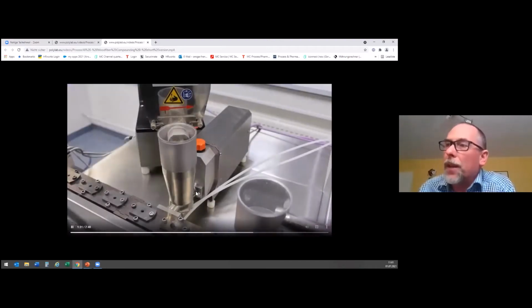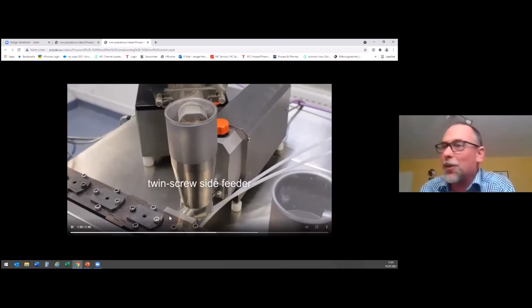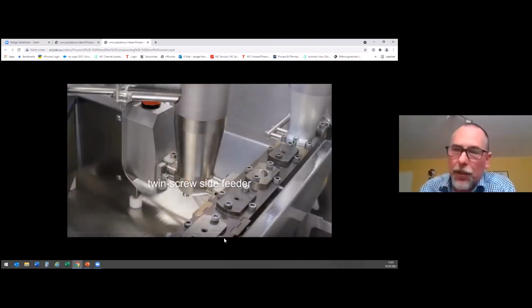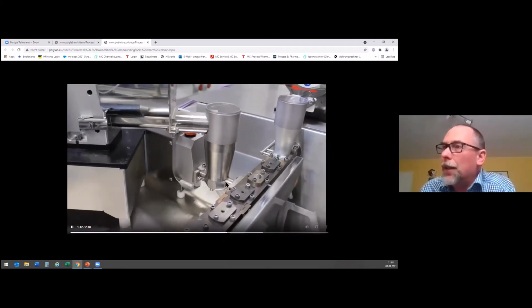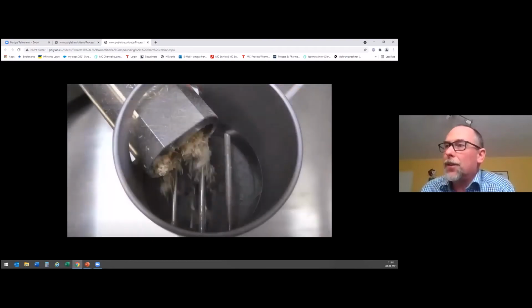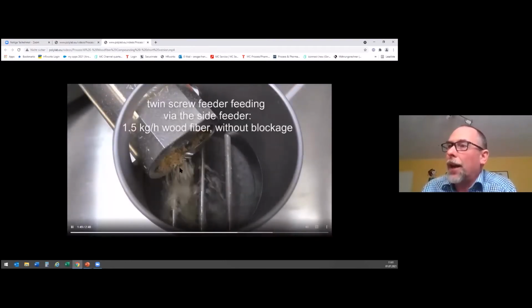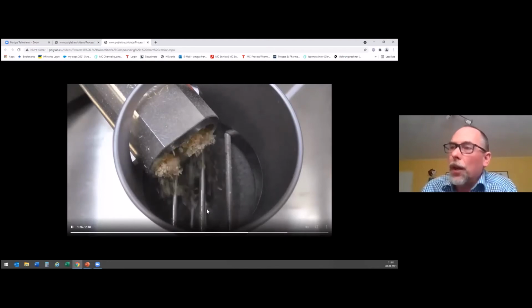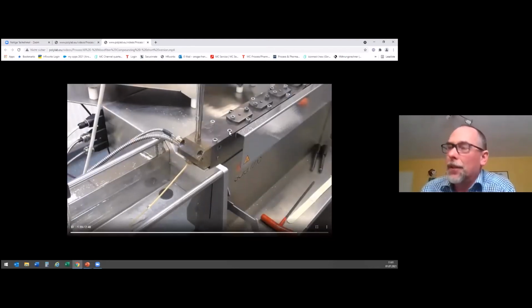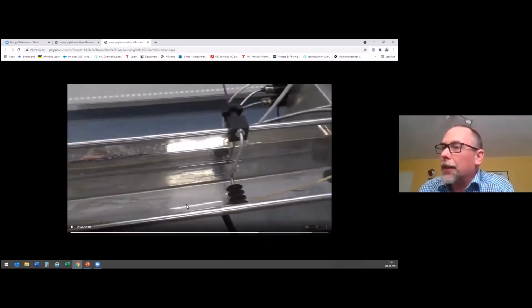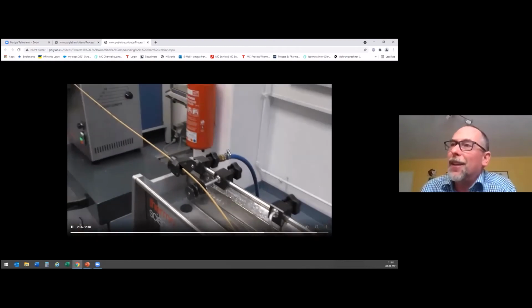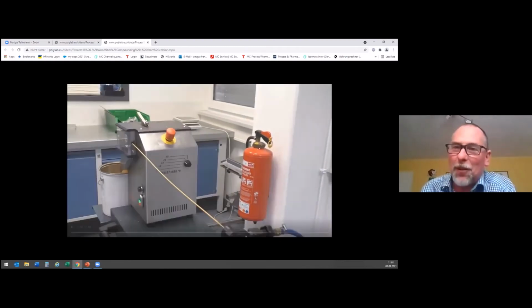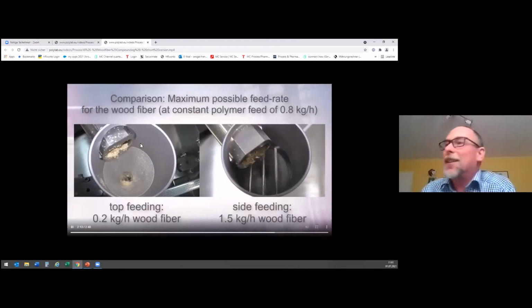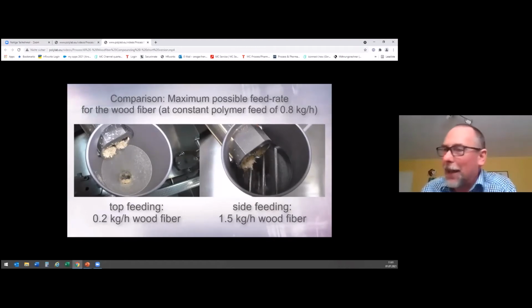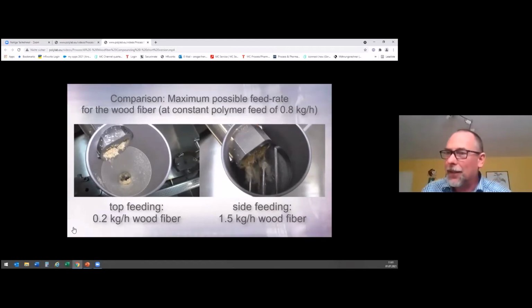Of course, side feeding is always possible when there is enough space on the screws. And it had been quite a new design for such a small extruder to use a twin screw side feeder to push the wood fibers into the extruder itself. So here you see the same or higher throughput of wood fibers, and below there are 2 parallel screws running only for the feeding purpose and pushing them into the extruder. So you see here the strand is collected, cooled in a water bath, and then either we could go for a 3D filament with a spooler, for example, but here it's a very standard process using a cutting system and creating new pellets. Okay, so good.